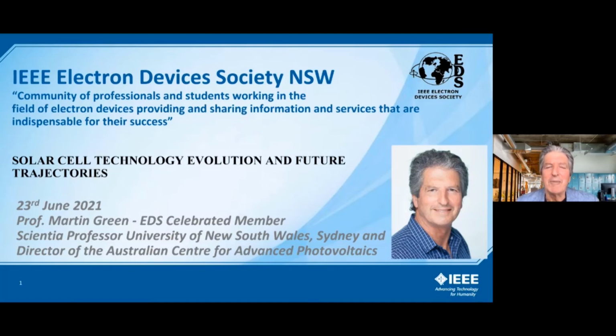So I mentioned the industry used to use boron as a dopant. It used to have a lot of interactions with oxygen and iron elements and light. So that combination created defects that were metastable within the material and could be seen in a drop in module performance or an increase if you got rid of them.